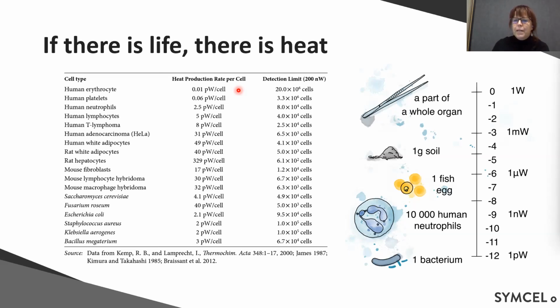So when we talk about microcalorimetry, it means that we can measure in the microwatt range. We can actually measure sub-microwatt, we can go down. So in this area, this is where microcalorimetry can measure a sample. And if we just see that one bacterium, like an E. coli, will produce about 2 picowatt, so you only need about 100 to 100,000 cells to be able to detect them in the calorimeter. And we know that bacteria replicate quite fast. So even if you put a few in from the beginning, it doesn't take very long until you have a measurable signal in the calorimeter.